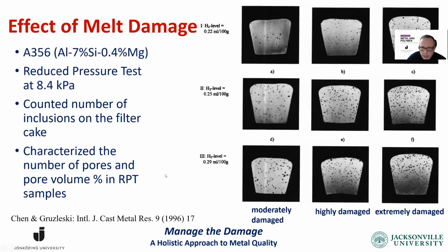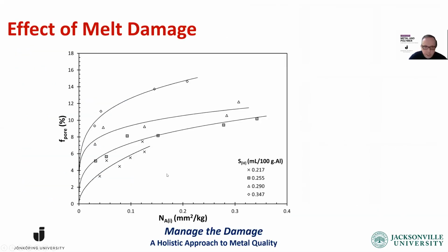So I took their data and I took a second look at it. Here on the x-axis, you see the number of inclusions that they caught. So that's a measure of the damage given to the metal. On the y-axis, you see the volume percentage of pores that they catch on the RPT specimens. And different curves are for different hydrogen contents. And when we plot them,